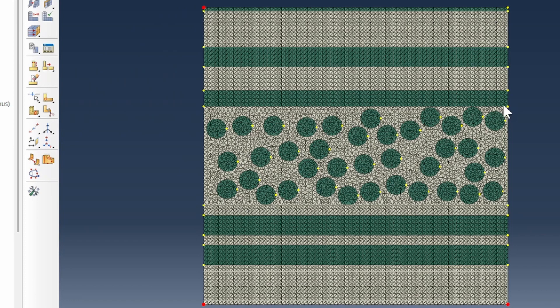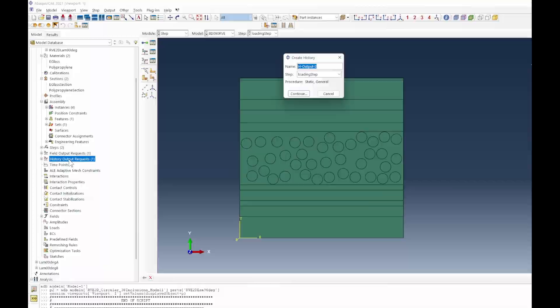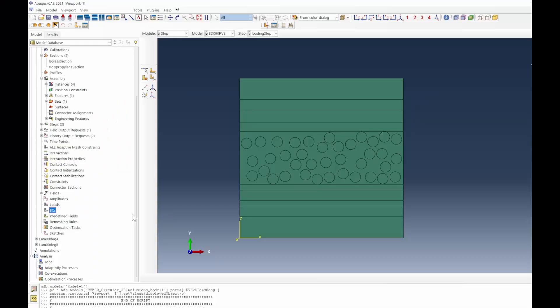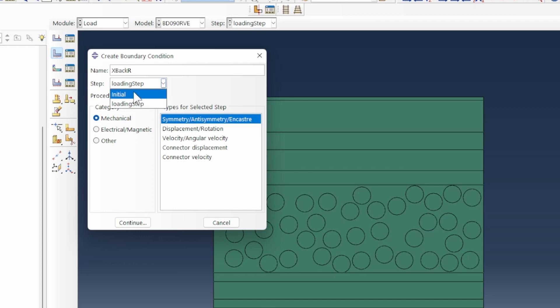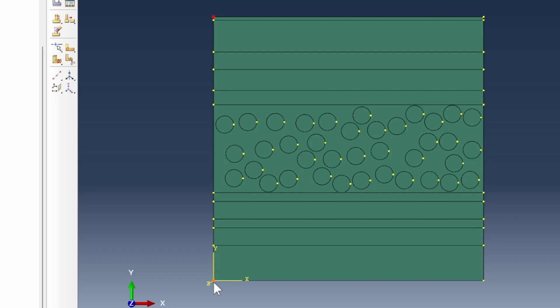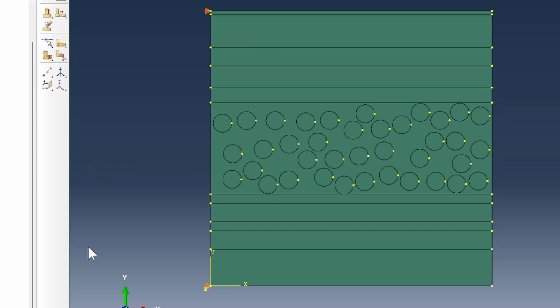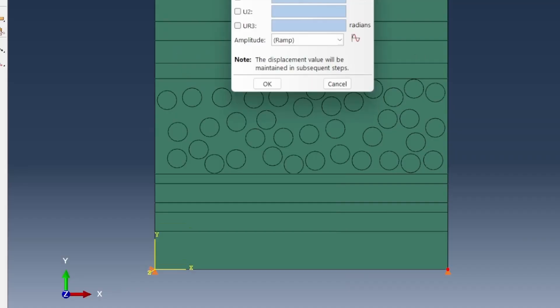We create a static general loading step and set up corner node history output requesting RF1, U1, and U2. We apply boundary conditions: an X-back roller (initial displacement BC) attached to the back corner nodes only, and a Y-base roller attached to the other corner points in the Y direction. The load X is a loading step displacement of 22.5 microns, which is 10% of the 225-micron edge length. We rename this case 'Xtense'.